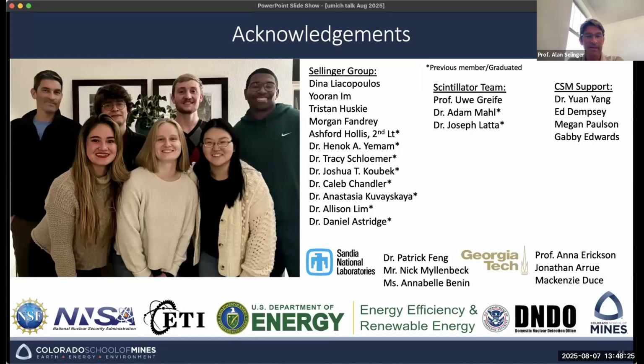because it's a dangerous process, and the companies that work on this need to be concerned about this because they're working on hundreds or thousands of kilograms doing this conversion. So it's a really big safety process, not only because of the potential for these exothermic reactions, but also because these are volatile materials. If you're heating up these materials, they can evaporate and become airborne and be breathed in. So there are a lot of things to be concerned about, and it's one of the reasons why we are shifting our focus to silicones and organic glass now.